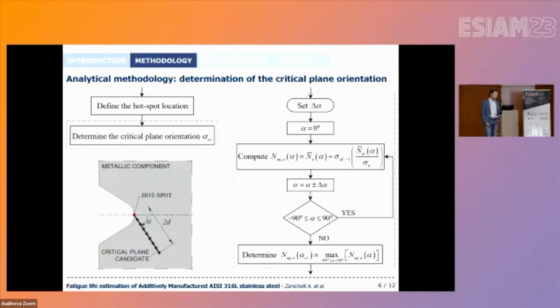So then both the amplitude and the mean value of the normal stress component acting on the corresponding plane are computed in many equally spaced points belonging to the segment, as you can see in the figure. And then they are averaged, and their averaged values, N_A and N_M overlined, are employed to compute the fatigue parameter, the equivalent N_A, which is given by the equation shown here according to the Carpinteri criterion. So then a new material plane is considered, and this procedure is iterated for all the material planes inward the structural component. So finally, the orientation alpha critical, which maximizes the fatigue parameter, is assumed to be the critical plane orientation.